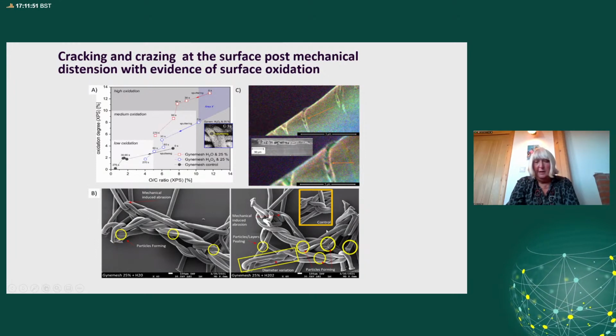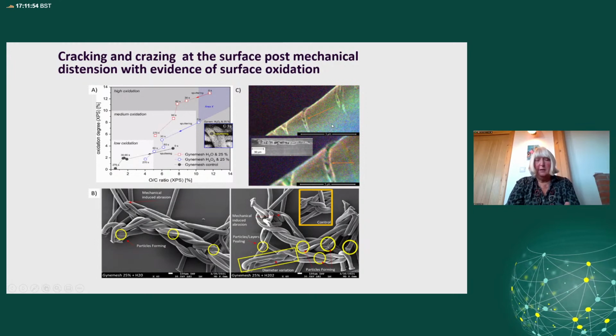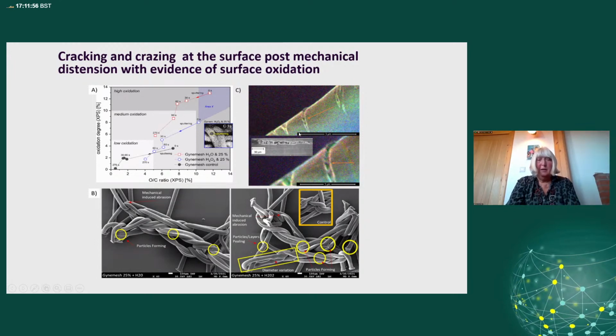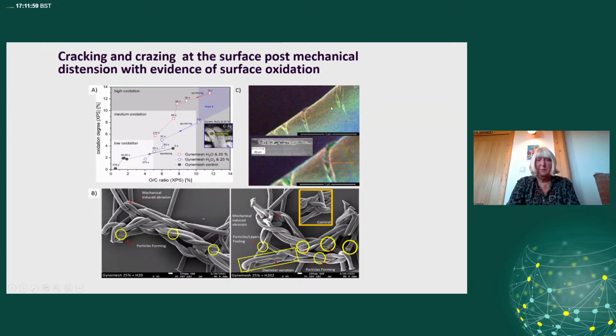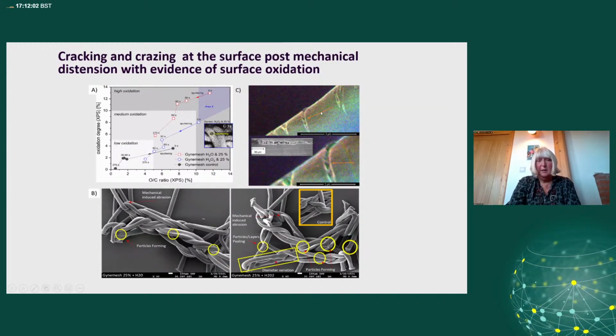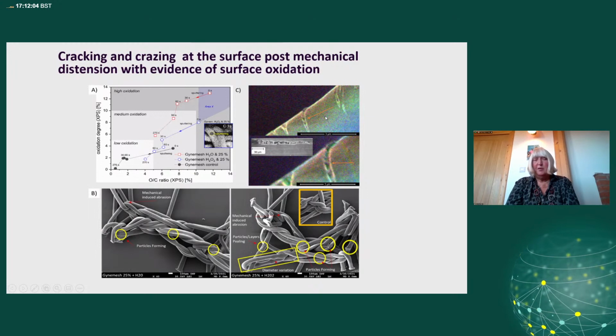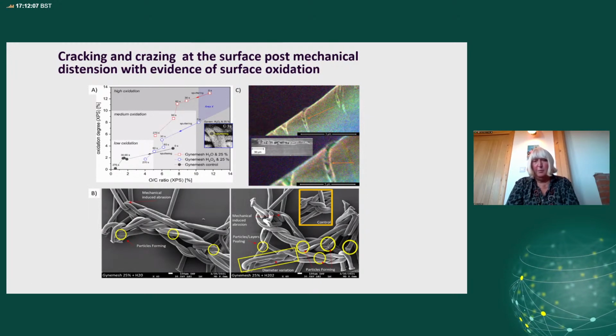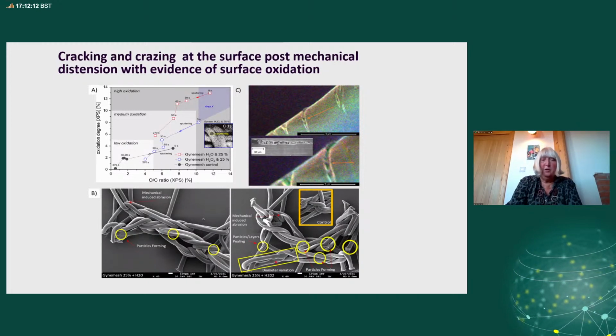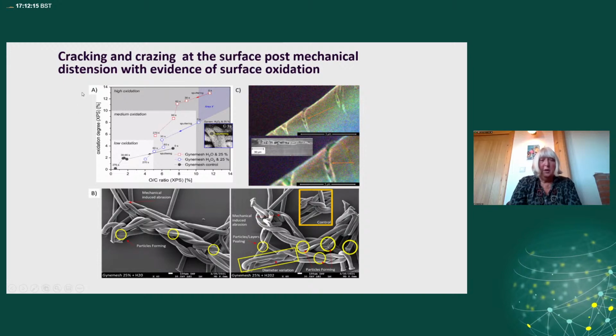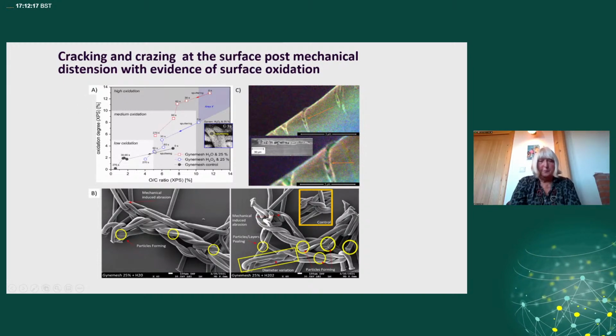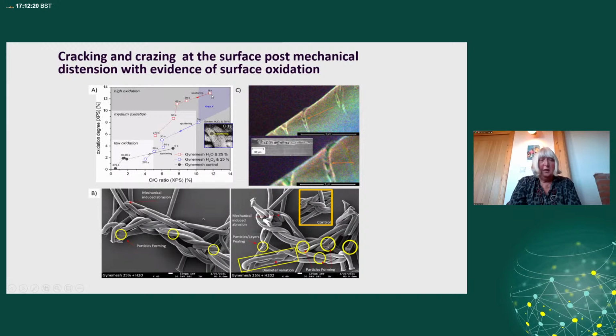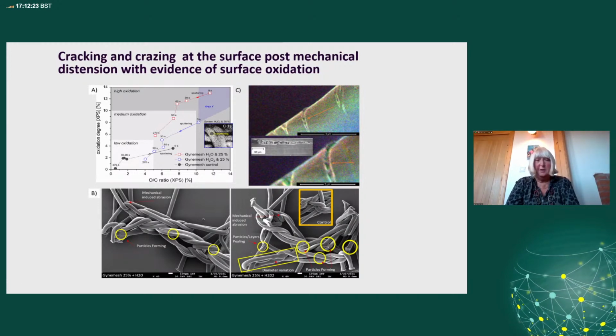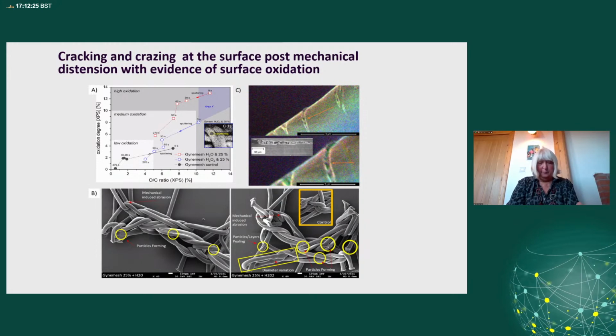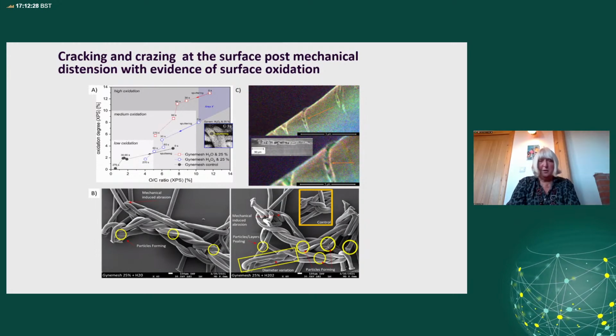But what we found in nearly all places, after both mechanical distension and oxidative stress, is evidence of cracking and crazing at the surface. Now, this looks very dramatic, but we're talking about defects of about 5 micron. They do not go through the bulk material, but they do affect the surface. But the critical bit is when you look at what's actually happening at the bonds, we find evidence of oxidation. And there are bonds indicating that the material becomes highly oxidized when subject to hydrogen peroxide, particularly when put under mechanical stress.